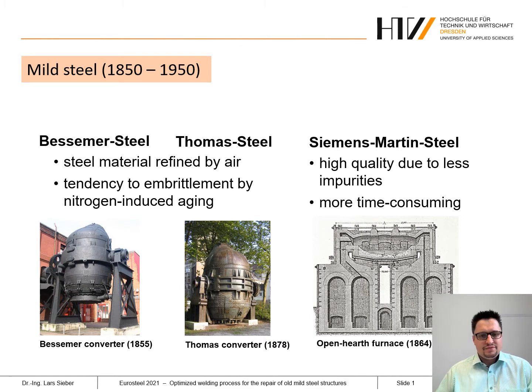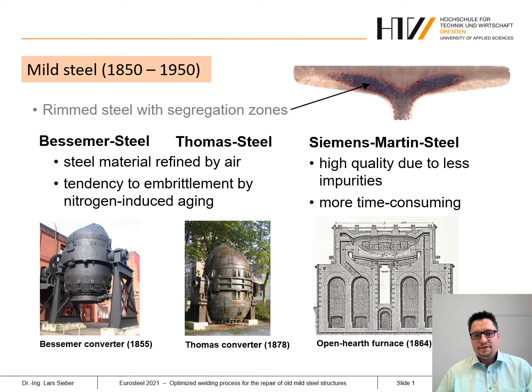All these two or three materials have been, in the 1930s and 1940s, rimmed steels with a typical segregation zone in the middle, as you can see here, and also a perfect outer rim at the surface of the cross sections. To weld in this outer rim is very easy, because you only have to make sure that you do not melt this segregation during the welding.